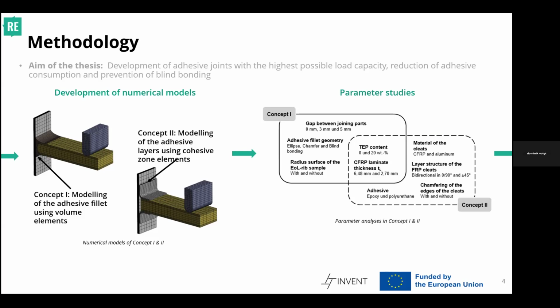For example, I studied parameters like geometry parameters of the adhesive fillet, material parameters like different adhesives, for example, epoxy adhesive or polyurethane. And for both concepts, I also studied the influence of the percentage of TEPs, which are particles which expand by heat and therefore destroy the adhesive layer to debond my adherends.